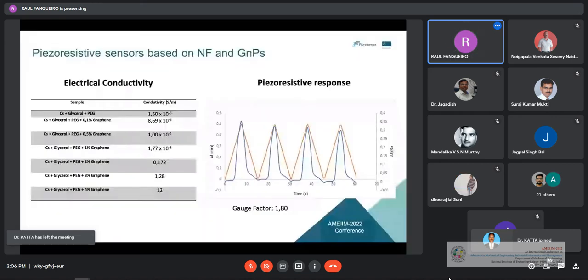So in orange, you can see the mechanical response of the material in cyclic load, and in blue the electrical response of the material at the same time. And as you can see, both curves are following the same pattern, which means that when we define a correlation between these two factors, we can have this material being used as a sensor to sense deformations in the material and in different applications.